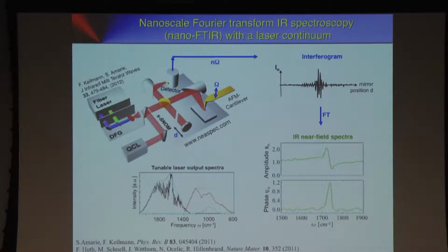In a standard Fourier transform spectrometer, you have the sample outside the interferometer, so either in front of the detector or in front of the beam splitter. And then you get only the intensity spectrum. But we place the tip and the sample intentionally inside the interferometer, and because of that we get both amplitude and phase information. So we get amplitude and phase, and this is important if you want to get the complex valued information about a sample. And you will see later on that the imaginary part of the spectra is related to the absorption. Also, we have here a scattering experiment.